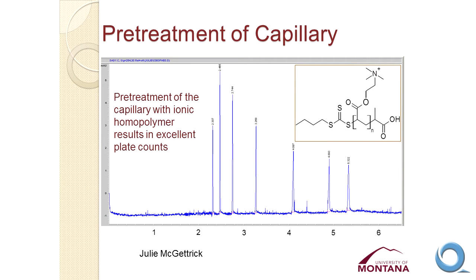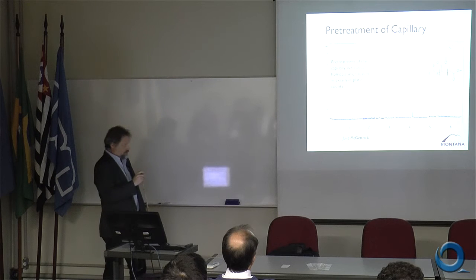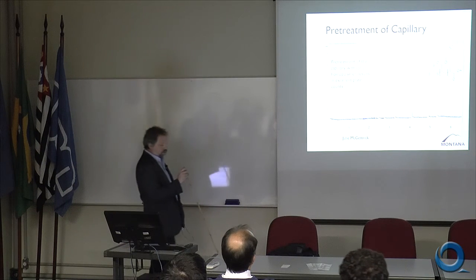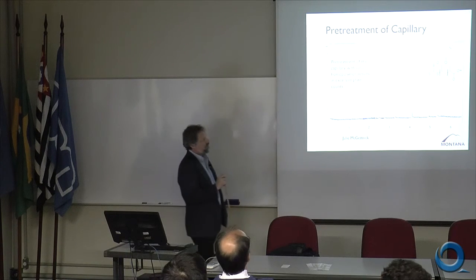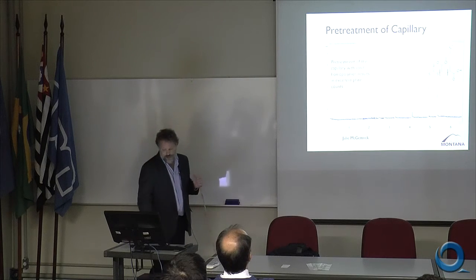Since I've been here, Julie, the student, has done a very nice job of fixing this problem. What she does is to modify the capillary walls first with this homopolymer, which is not hydrophobic, and then we can use those cationic nanoparticles and get very nice high-efficiency separations again. So this demonstrates clearly that it was the interaction at the capillary walls that was causing the problem, and that those interactions at those capillary walls are quite strong.